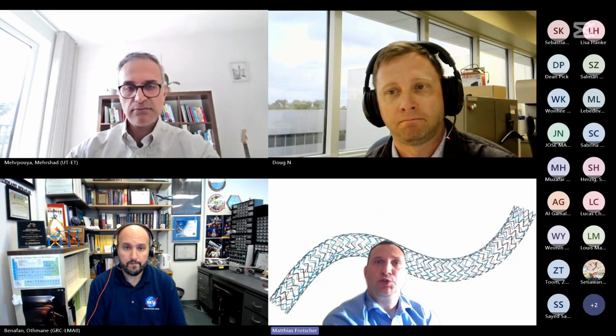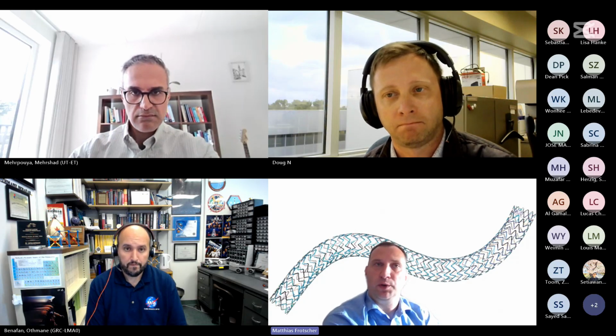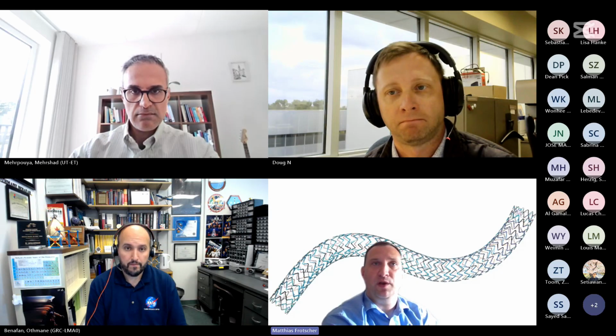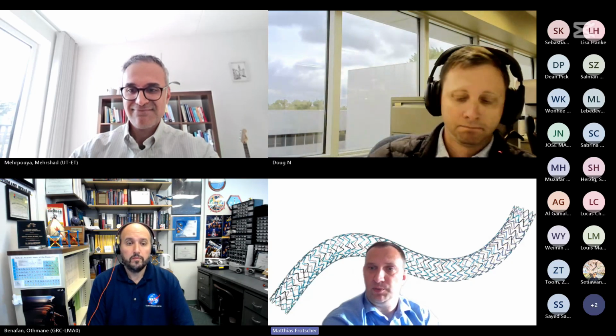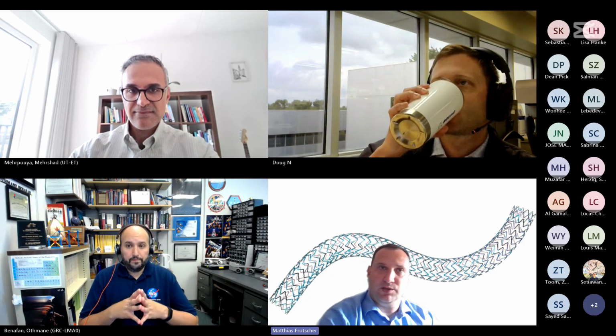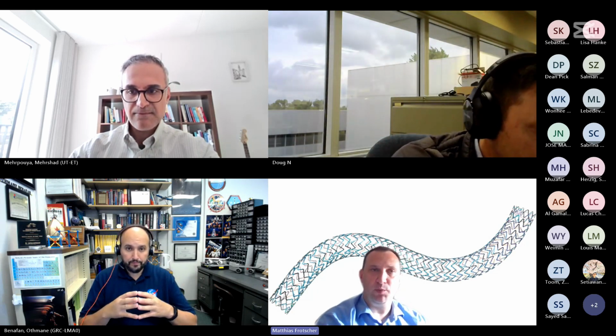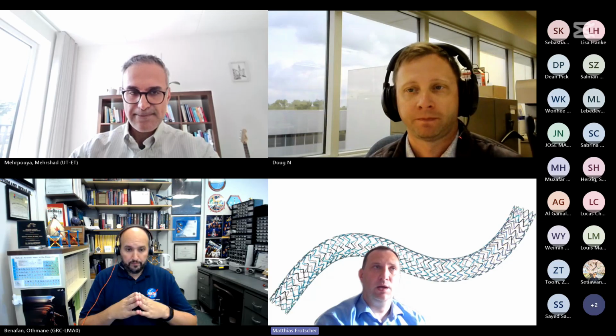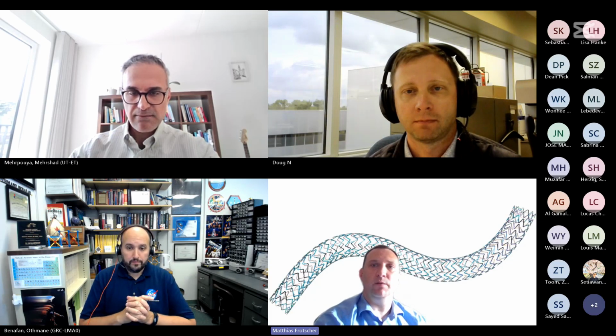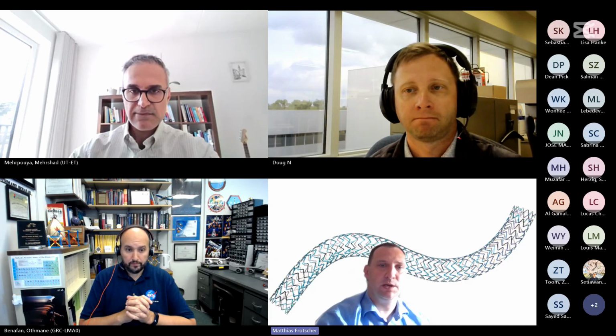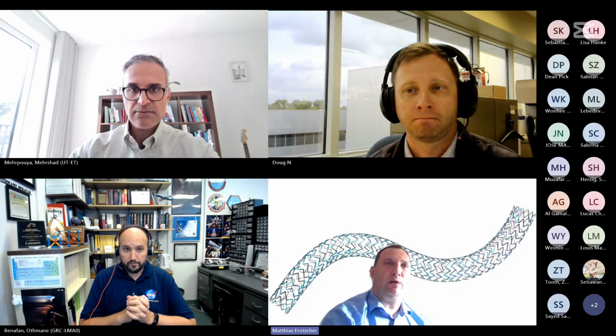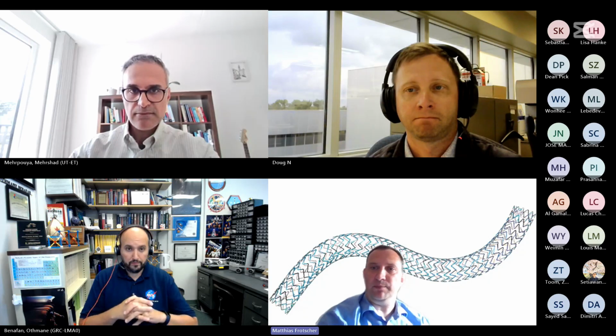A different question would be, do we need inclusion-specific counting? For example, do we want to know an intermetallic hafnium phase and separate these from, let's say, titanium carbides or oxygen-rich intermetallic phases? Do we want to separate those inclusion types? At the moment, we are not doing that. We are basically counting porosity and inclusions as one, and we also don't differentiate between carbides and oxides. It's just a matter of what kind of impurity you have in your material and what your acceptance criteria are for a specific application at the moment.